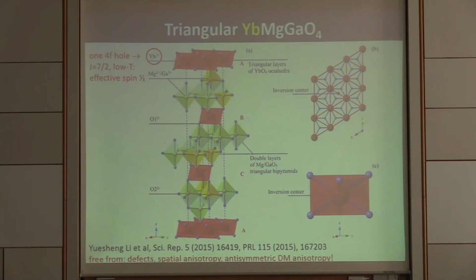In the last few minutes, I'll now discuss another triangular material, but here the magnetic moment is not from iridium, but rather from a rare earth. So here we have ytterbium 3+, and that means that we have just one hole in the 4f shell. We have 13 electrons, one hole, and that has J equals 7/2 total angular momentum, and there's crystal field splitting, and at low temperature we have a Kramers doublet with an effective spin 1/2.